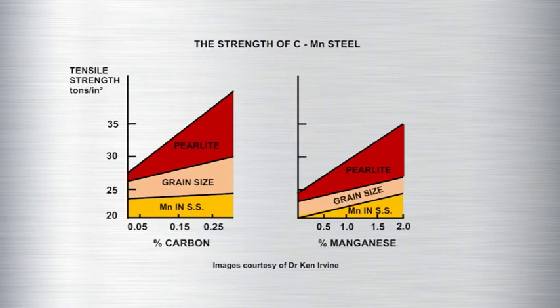But on the other hand, there were about 6 or 8 solid solution hardening factors which we identified and were able to quantify, because you could take these by making steels which contain just simply silicon additions and manganese additions and chromium additions and nickel additions and so forth. And by taking out the basic strength out of that, you could say what the solid solution hardening was. And of course, things like nickel were very little solid solution hardening, whereas things like phosphorus were high degrees of solid solution hardening.